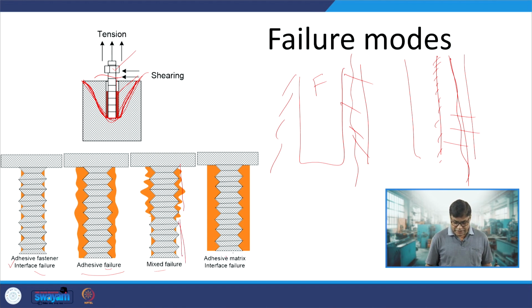Okay. And this is the adhesive matrix failure, where the matrix in which the hole was drilled, if the bonding between the adhesive and the matrix is not good, then the adhesive matrix failure takes place.